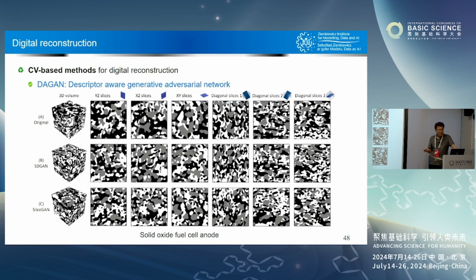The worst thing about the GAN model is, let's say you use 50 layers of neural network. It may be worse than your 40 layers of neural network. By increasing the layers or increasing iterations, it's not guaranteed your result gets better. But with our model, it converges. As the iteration goes, the result is definitely getting better. As the layers increase, the result is definitely getting better, because we have the descriptor there to explicitly control the iterative process.